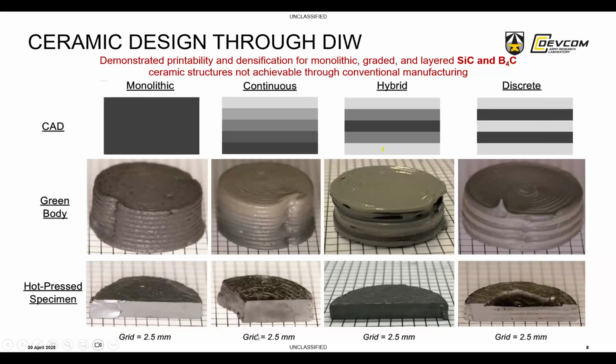Okay, sorry about that. So this second column, continuous, basically what we did was we started with full boron carbide, and we were able to change the composition as we built the part. 10% volume change in composition each layer until we got to full silicon carbide to create a sort of functional grading. And then we also created these discrete layers. The idea behind this was mainly for soldier protection. The idea was in advanced ceramics, can we influence crack propagation through a material by changing composition?